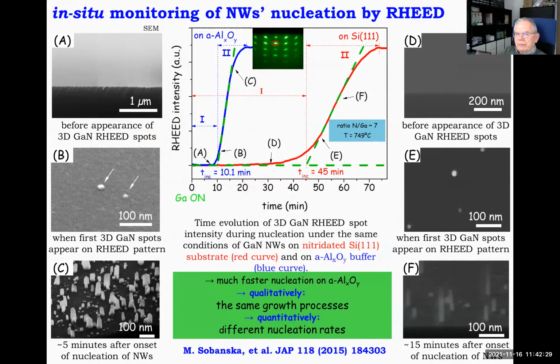I showed you that we use a quadrupole QMS for studying the processes, but the same can be done by RHEED. In this case, this is a final RHEED pattern. We know where this spot is going to appear. So from the very beginning, we monitor the intensity of this spot, starting from the point when we open the gallium cell. Similar to the QMS profile, we see incubation, so there is no gallium nitride on the surface at all, then an increase, the nucleation stage. So this tool can also be used for monitoring the evolution of gallium nitride on the surface.